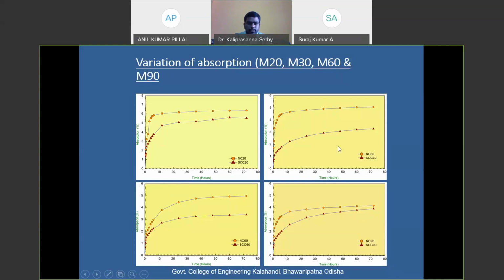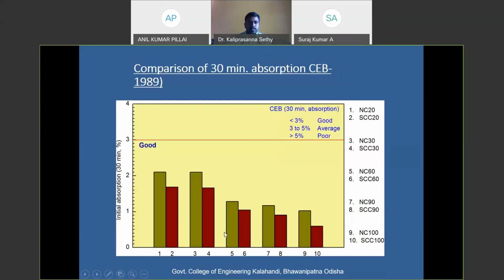For all the cases you can see, we found the self compacting concrete is showing very low absorption value than that of normal concrete. It might be due to the fine contents in the self compacting concrete. So this is the bar chart plotted for 30-minute absorption values.